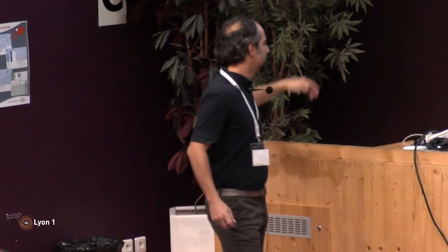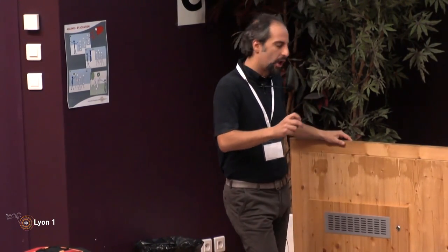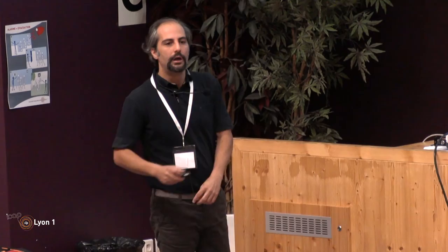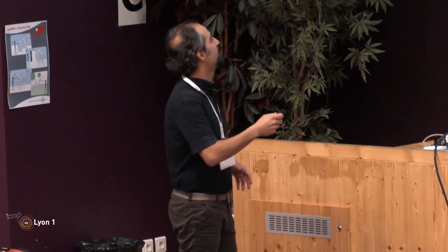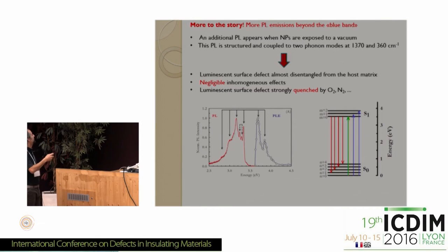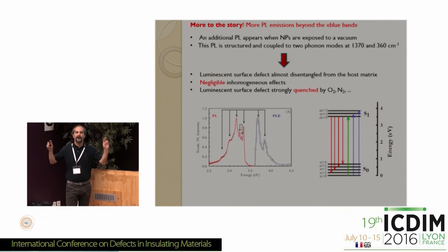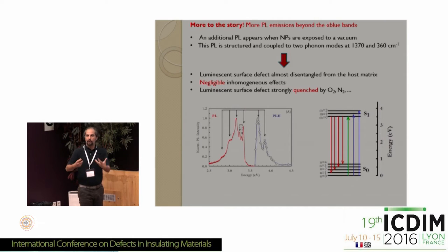And the properties of silicon nanoparticles are not so simple, in the sense that not only do they give rise to this ubiquitous blue emission, which is very intense and interesting for the reason I said, but there are also additional emissions which are all different from what you observe in the bulk. For instance, some recent work from our group showed that when you expose nanoparticles to a vacuum, meaning you just put them in a cryostat and remove all air, you immediately see the appearance of another luminescent signal, which is distinct from the blue luminescence, which is peculiar to these nanoparticles, not found in bulk.